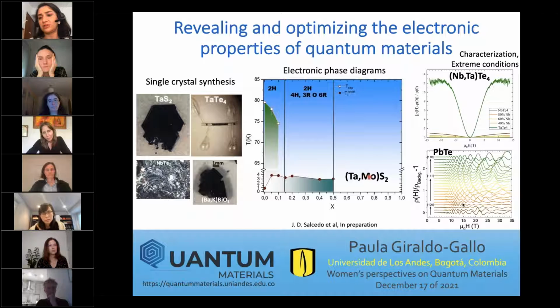And extreme conditions, these are some examples of beautiful magnetoresistance measurements that we have done in this Weyl semimetal candidate, niobium tantalum tellurium 4, in which we observe a nice evolution of the magnetoresistance with the dopant, and for magnetic fields that we have available here in the lab up to 15 Tesla. But when 15 Tesla are not enough, we go and use our beautiful contacts and we apply for magnet time in high magnetic field facilities. And we have a lot of experience using the high magnetic field lab in Tallahassee, Florida.